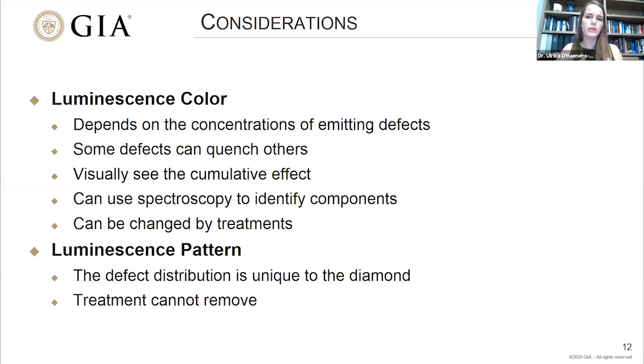A lot of people think of non-fluorescent diamond as being purer than fluorescing diamonds, but that's not necessarily the case. In fact, one of the defects that causes most of the fluorescence is the N3 defect. If you have another defect present that's an A center, which are nitrogen pairs, that nitrogen pair center is able to effectively steal the fluorescence, absorb the fluorescence of the N3 defect.